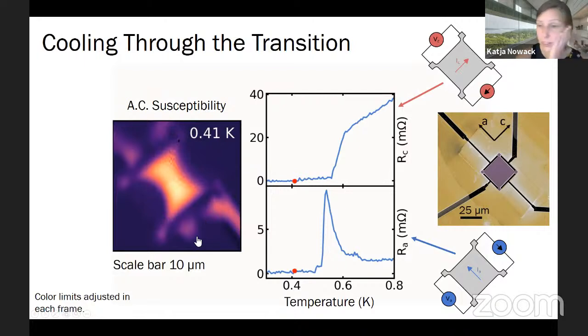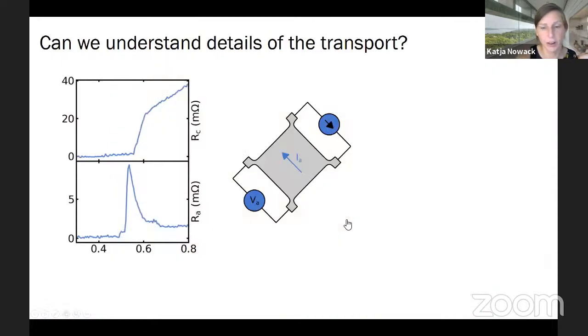Okay, so we found a very simple answer. And maybe in hindsight, this may have been obvious. We found a simple answer to what is happening in this unusual transport behavior, and that is just that the superconductivity turns on in this device in a very non-uniform fashion. All right, and we can even use this information to understand more details about the transport curve. For instance, we can understand why the inferred resistance in this measurement spikes here.